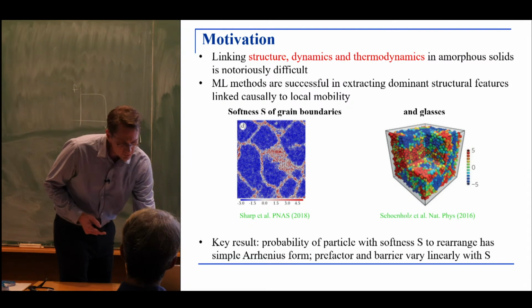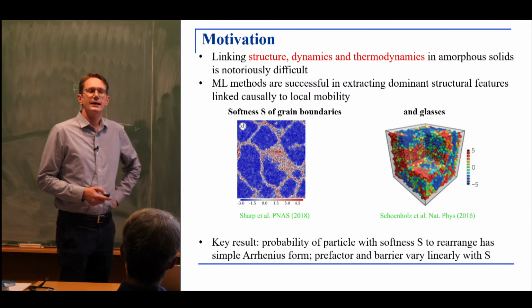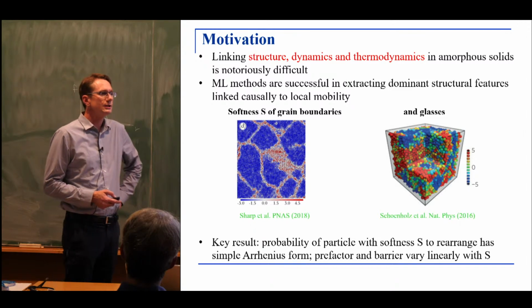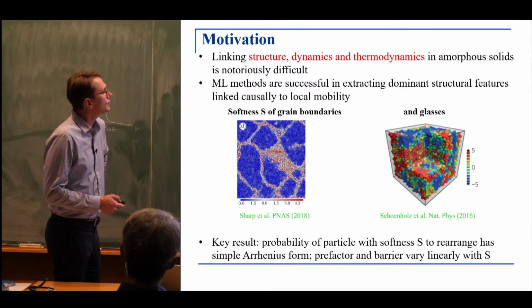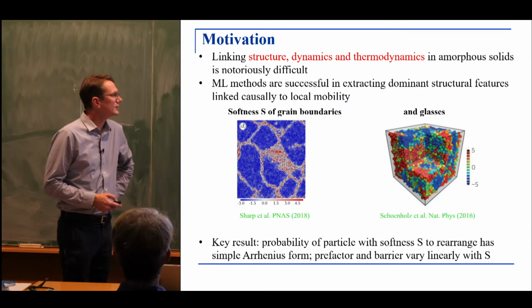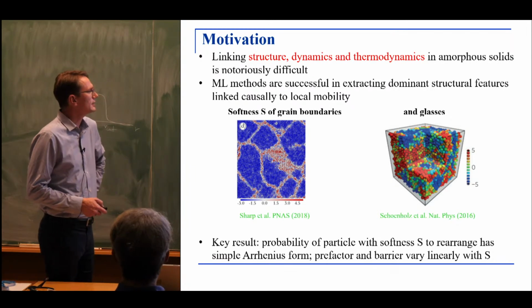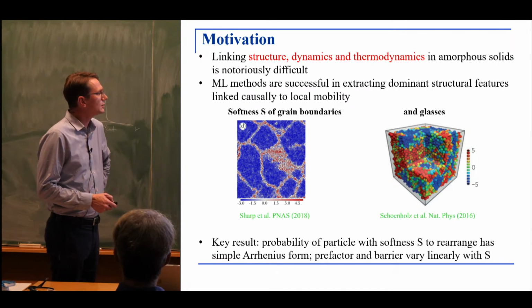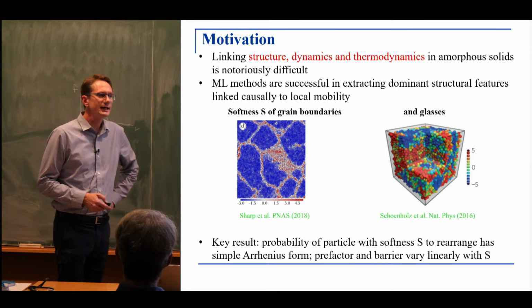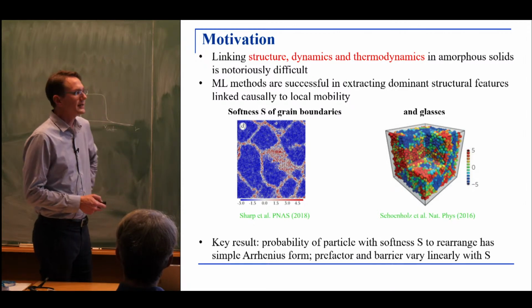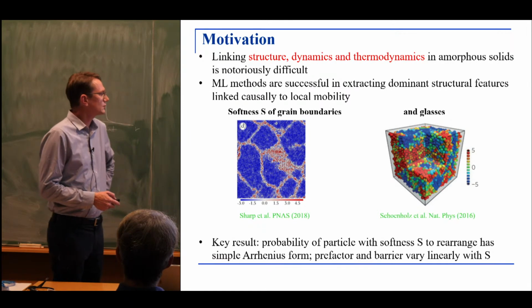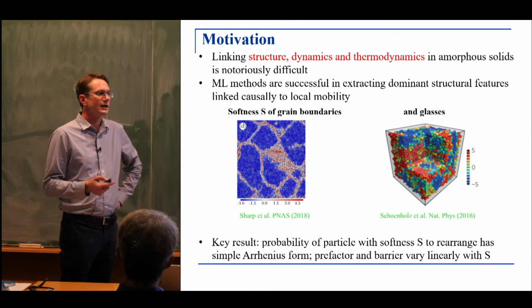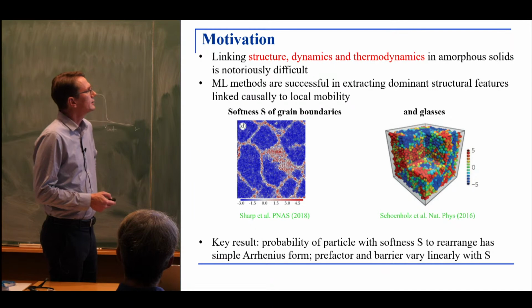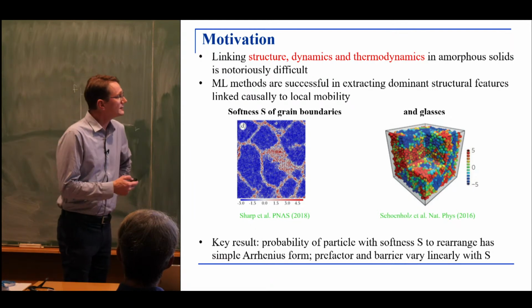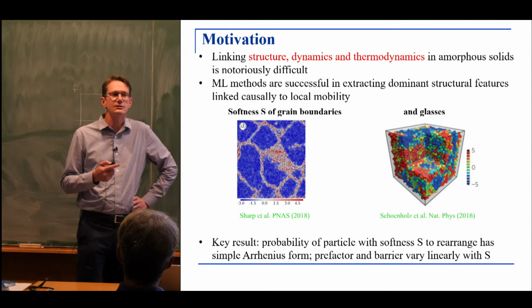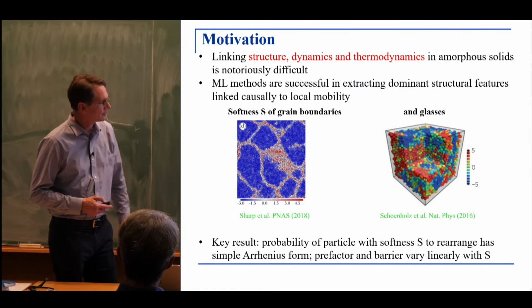One thing that resonated with me really is that this method does not only produce pretty pictures, but there's more that one can get out of this concept. For instance, one can inquire into the temperature dependence of the probability of a particle with a certain softness S, and then one finds that it has a simple Arrhenius form, so one can ascribe an energy barrier and a prefactor to that, and one can associate that with the degree of softness. So this establishes quite robustly, I think, that there is a relationship between structure and dynamics.